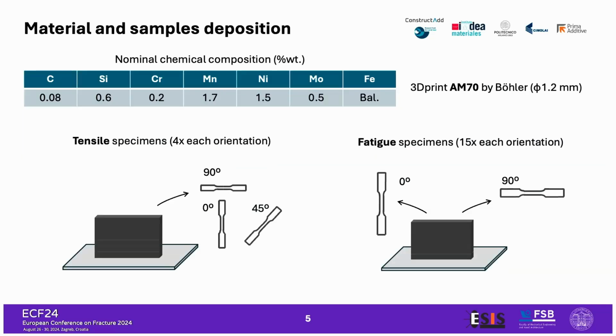Regarding the steel, in the first phases of the project, different steel grades were analyzed and studied, and finally we came up with the composition that you see in the slide. So we are talking about a very low carbon steel with a weight percentage of carbon less than 0.1% and low alloyed with silicon, chromium, molybdenum, manganese, and nickel. In particular, the wire feedstock for the process was provided by Bohler. It is a 3D Print AM70 feedstock with a diameter of 1.2 millimeters.